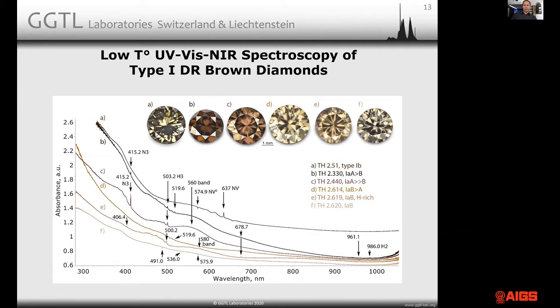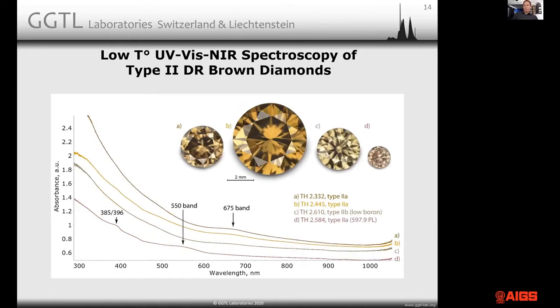And you can see that depending on what type the stone is, the UV visible spectrum varies somewhat, but they all coincide in the fact that they're mostly just a continuum, a flat continuum, which is the result of brown coloration. Type 2A diamonds, you basically see the same thing, just that the overlaying bands are even much less frequent. So for type 2A diamonds and type 2B, there's type 2B diamonds here as well, you see just a couple of broad bands that overlay this continuum.